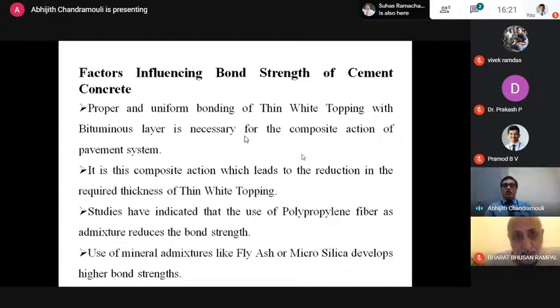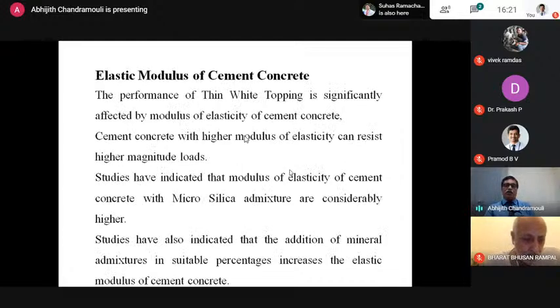Use of polypropylene fibers has been thought about as an additive to improve the flexural strength of the thin white topping concrete. The studies have shown that whenever we have polypropylene fiber, the bond strength of the cement concrete with the existing bituminous concrete will be slightly lesser, because these polypropylene fibers at the interface will reduce the bond strength. So it has certain disadvantages. Use of mineral admixtures like fly ash and microsilica develops a better bond. If you are using them in the concrete, it definitely improves bond strength, as the studies have shown.